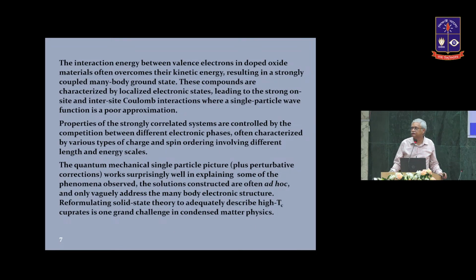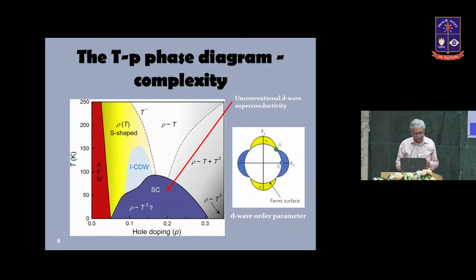Okay, so this is the electronic phase diagram of copper oxide superconductors, and I would just spend a minute on this. This is hole doping. This is where you dope the system. When you don't dope it, that is the undoped parent system, that is an antiferromagnetic insulator. And you can dope it via different techniques. As you dope, the antiferromagnetic order goes away at a certain doping, and you come to this point where superconductivity emerges, and it varies like this with hole doping.